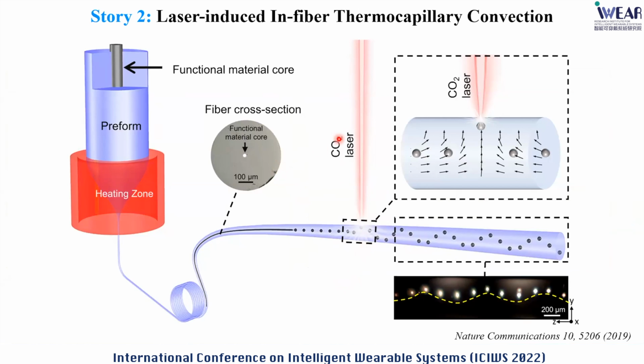Here, this is the so-called thermocapillary convection. Similarly, we use this semiconductor core here. After the fabrication, we see the core section of the fiber. Right in the center, we have the semiconductor core surrounded by the cladding. Firstly, we use the laser to trigger the so-called capillary instability, and this capillary instability transforms the continuous core into a chain of semiconductor spheres.